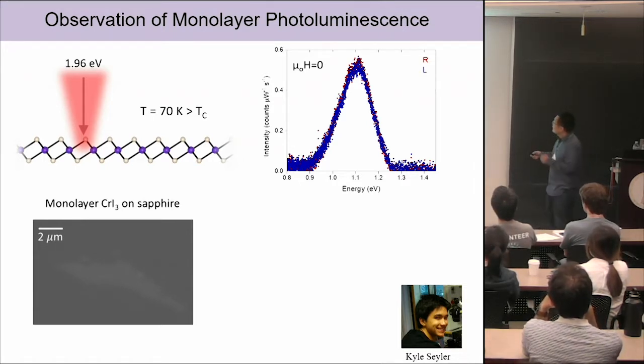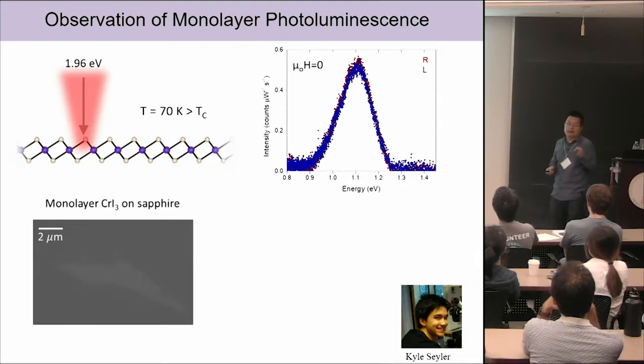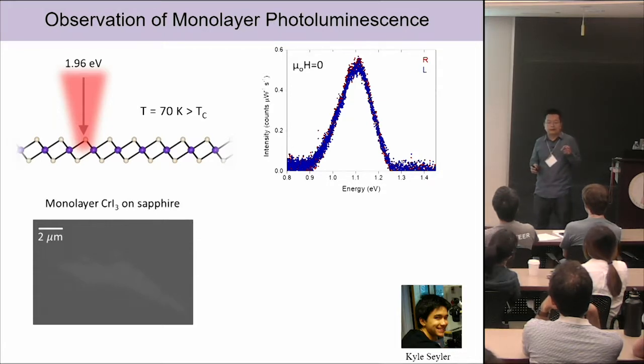The other thing I want to point out is that you can see the intensity is extremely weak. It's only like 0.4 counts per microwatt per second. It's at least two to three orders of magnitude smaller than, for example, transition metal dichalcogenides. Extremely weak. So you have to be very patient when you're taking this data.